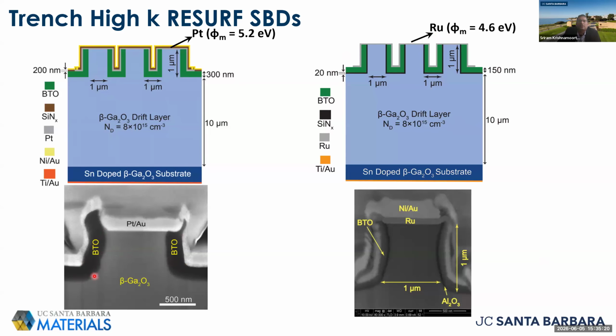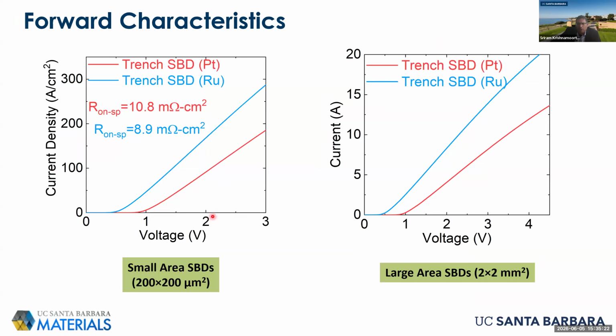And we were able to demonstrate tunability of the forward turn-on voltage. So lower work function metal like ruthenium gave us a lower turn-on voltage, still good current densities. And platinum gave us slightly higher turn-on voltage.